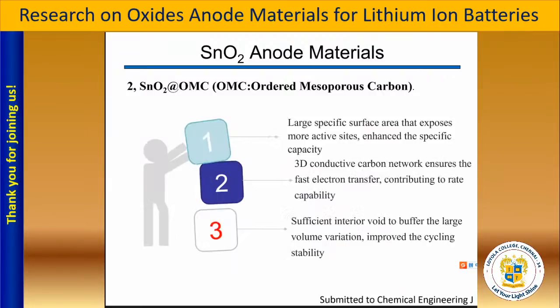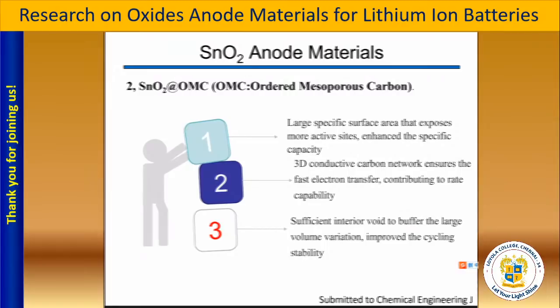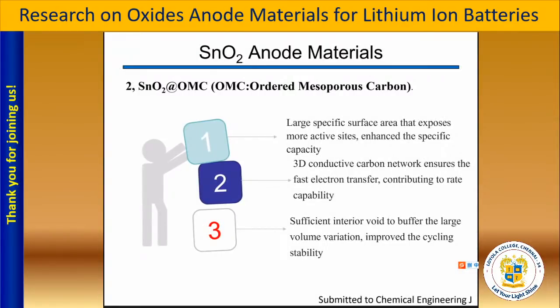So for this material, we think it has three results. First, the large specific surface area may help enhance the specific capacity. Second, a 3-dimension conductive carbon network ensures fast electron transfer, contributing to rate capability. And the voids or holes in the material are very helpful to buffer the large bulk expansion and improve cycling stability. So this is the first part.